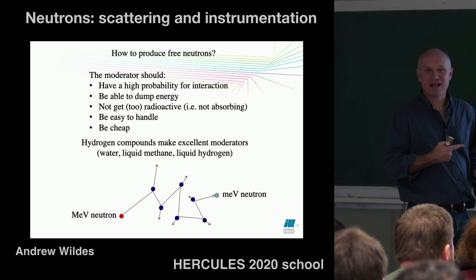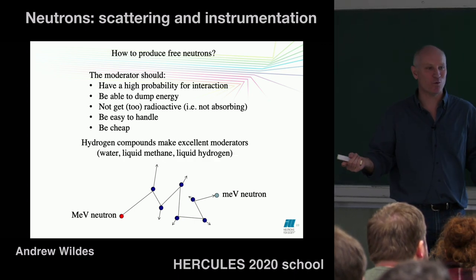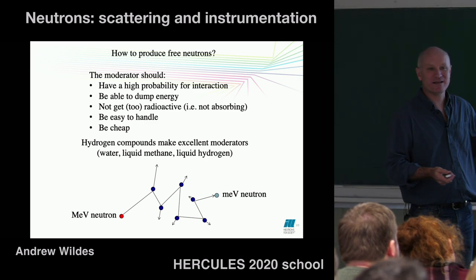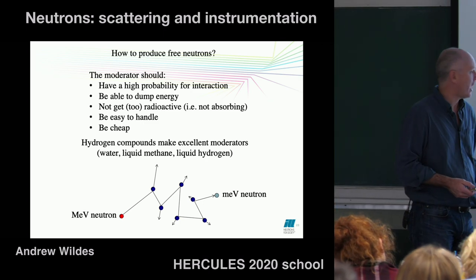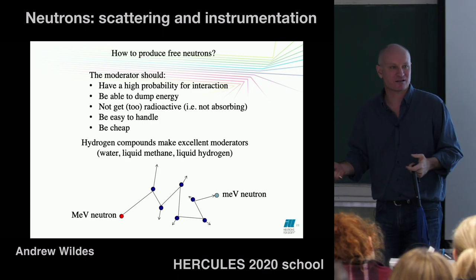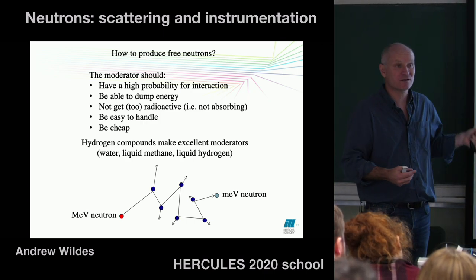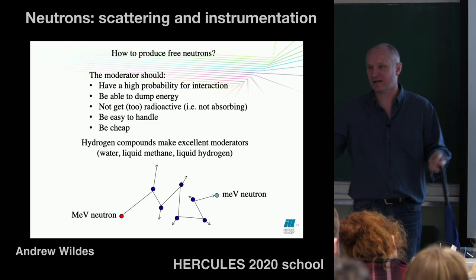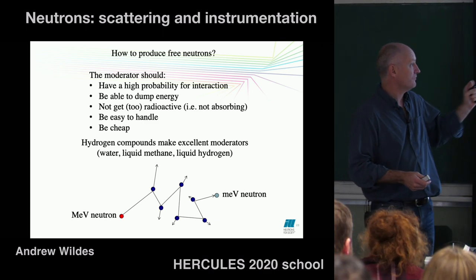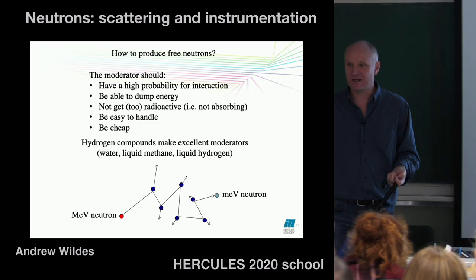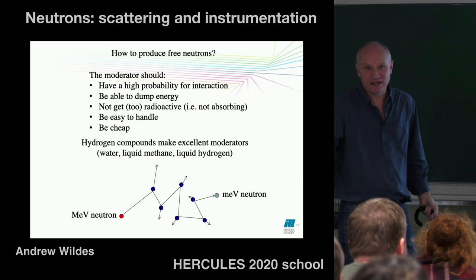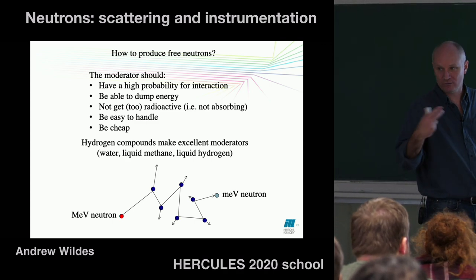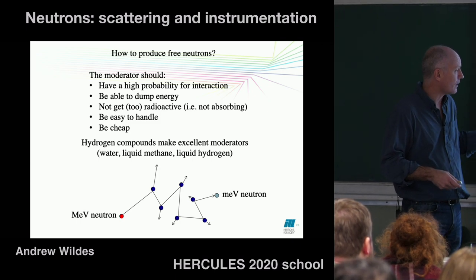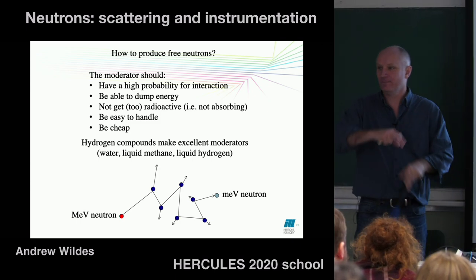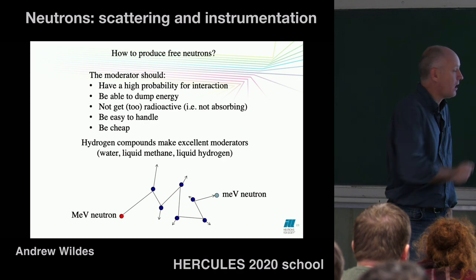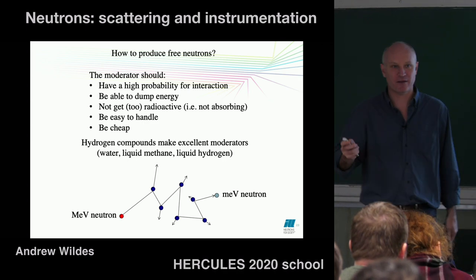Hydrogen makes an excellent moderator. And that's great, because water is cheap. Water is fantastic. Things like methane and hydrogen are very, very good moderators. They're generally liquids, so you can circulate the liquid, you can extract the heat very easily, and they don't get very radioactive. They're very easy to handle. They do get a little bit radioactive, of course, and you still need to worry about that. But generally, you'll find that all neutron sources have hydrogen-based moderators around them.